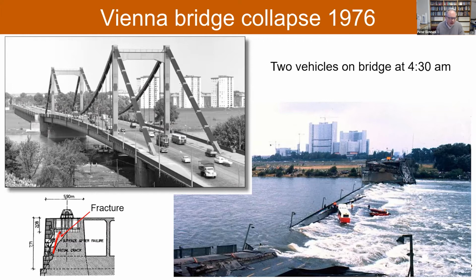What happened was that a crack had formed in the bridge support down here, just below this big arch here. And over time had spalled off part of the pillar here, which fell off and then the bridge collapsed. So that's just failure that accumulated over time in the support. It was not visible to the bridge inspections, so they couldn't see it. And then just one morning, out of the blue, for no apparent reason, it collapsed. So obviously the bridge is rebuilt. For those of you who have been to EGU, you have actually driven over the replacement bridge here in the subway train. The conference center is back here. And ironically, they put this bus back into circulation after this incident.